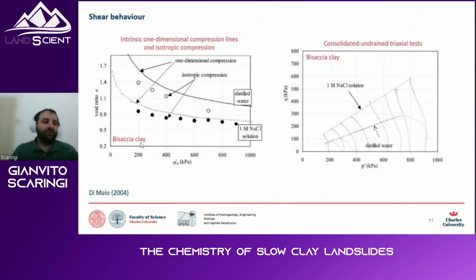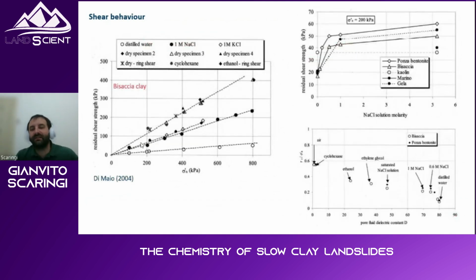And we see this weakening, of course, not only by the volumetric response, especially we see it in shear tests. Very briefly, you can conduct triaxial tests on samples that are saturated with water or with the salt solution. You will see that for active clays, typically the material in water has half the strength of that in salt solution, saying that when the clay is born at the bottom of the sea it is strong. The clay that we find now on the slopes and in the landslide is much, much weaker. This can be indeed a problem.